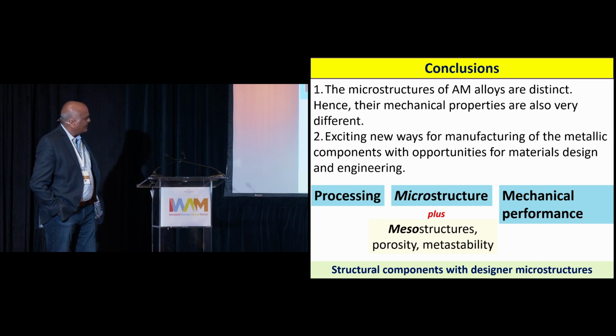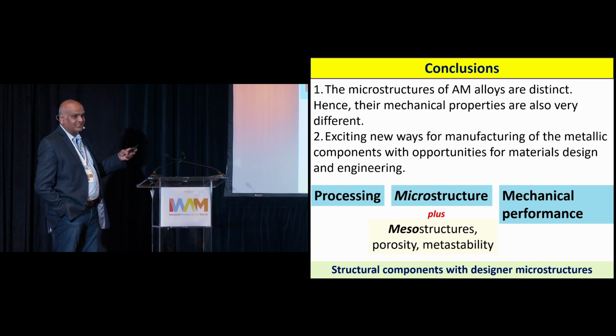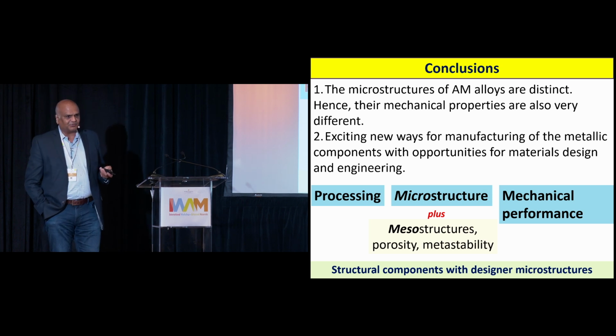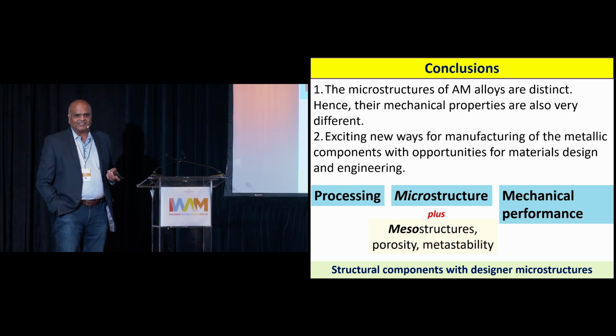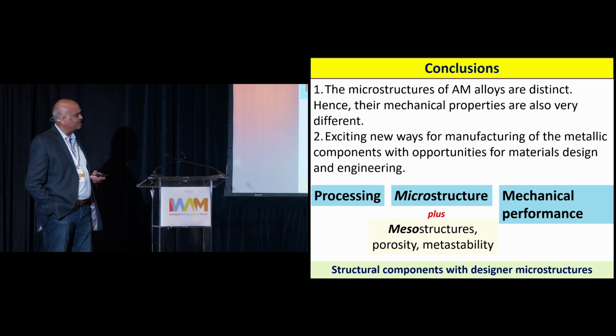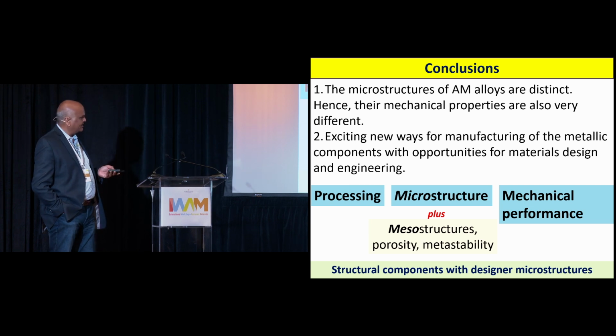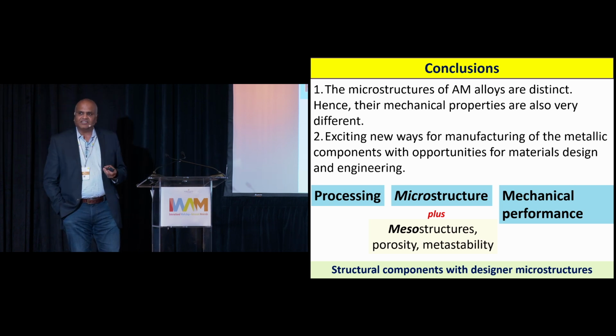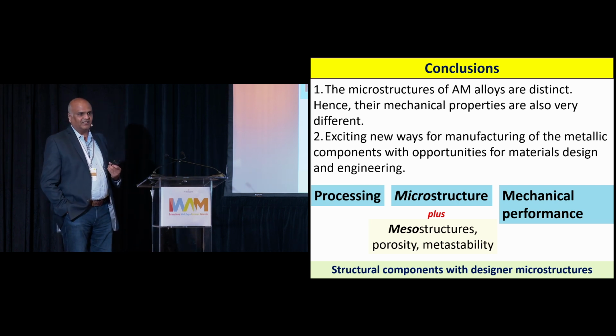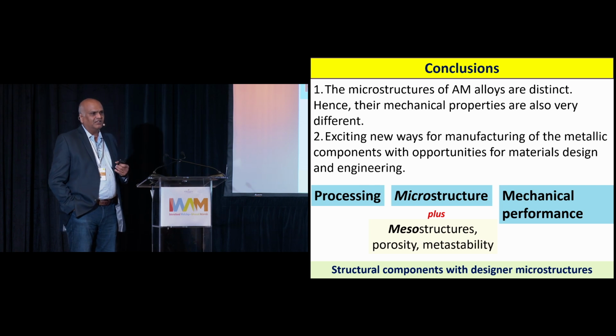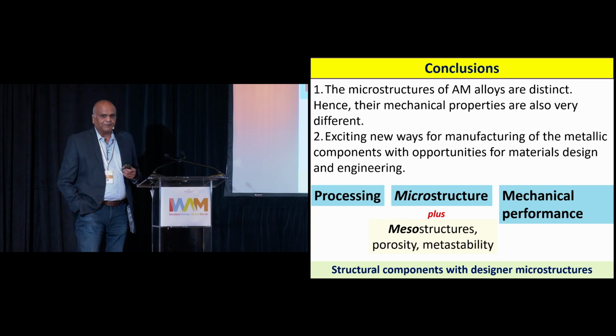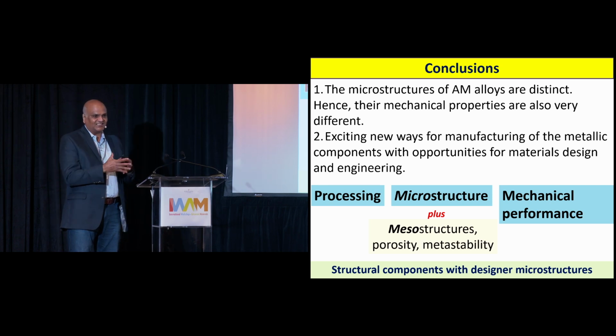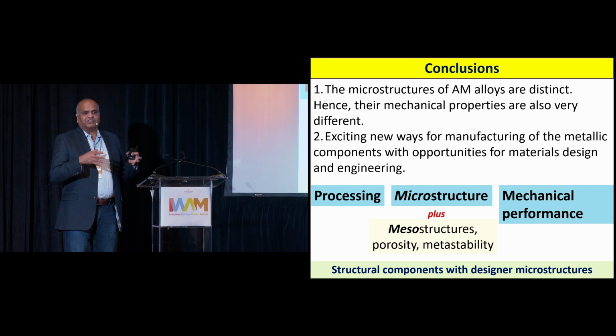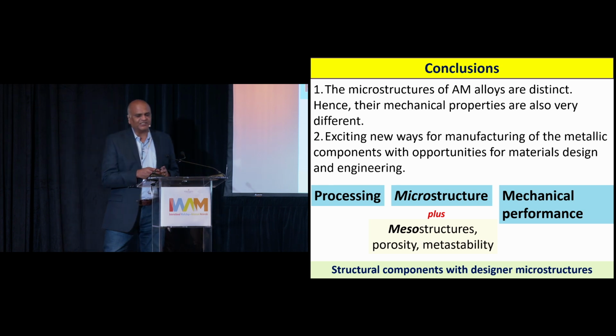Early on, I talked about these processing, microstructure, and mechanical performance connections. Right now, for this microstructure, we have to add all these additional features, meso-structures, etc. The thing that I didn't get a chance to talk about is the porosity. I skipped fatigue because that also affects the properties quite dramatically. And because of the rapid solidification conditions, sometimes you can also get metastable structures. That's another play you have. So the degrees of freedom that you have in terms of microstructural control increase substantially. And because you are printing 3D components directly, like a one-part synthesis that chemists talk about, you can have structural components with bespoke microstructures that are specifically designed for that very purpose. With that, thank you very much for your attention.